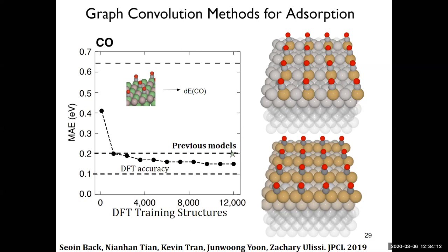Our previous models, based on me and Kevin sitting down and trying to featurize the surface, are this dashed line at about 0.2. These new models are doing quite a bit better. I would say we're approaching the DFT accuracy level, where I don't really trust the DFT calculations that much anymore, or there's numerical problems in how we're converging things that lead to some jiggle at that level.